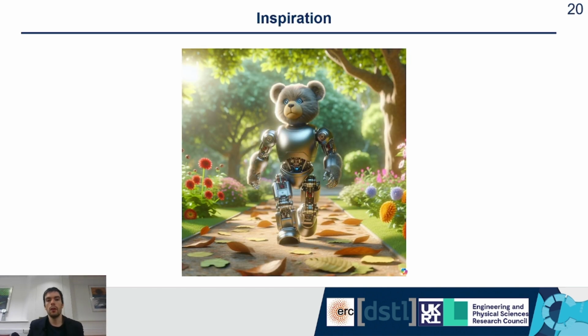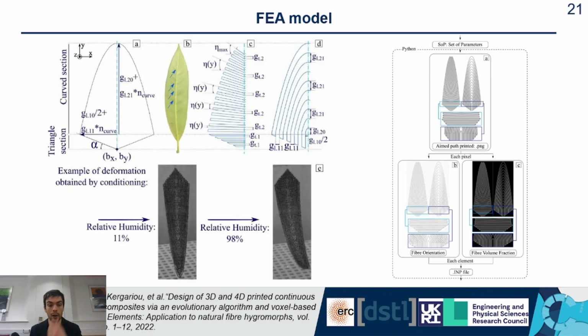We also wanted to create our own model, and so we were inspired by a walk in the park in which we saw leaves curl on the ground. So when they fall from the trees, a leaf dries and then tends to curl. So we wanted to see if we can reproduce an actuator that is able to curl the same as a dry leaf. So what we did is we looked at the back of the leaf, looked at the vein pattern on the back of the leaf, created a layer which has a similar pattern basically, and then the second layer in D shows the second layer which is transverse to the initial vein pattern layer.